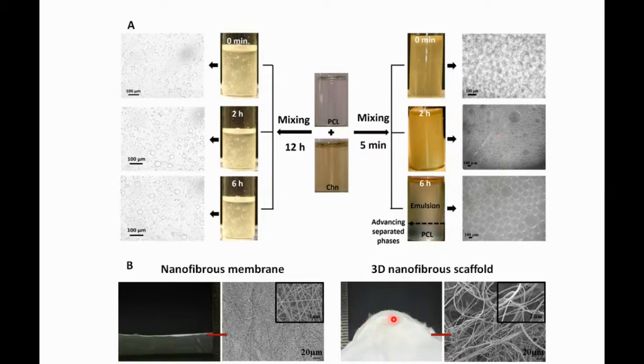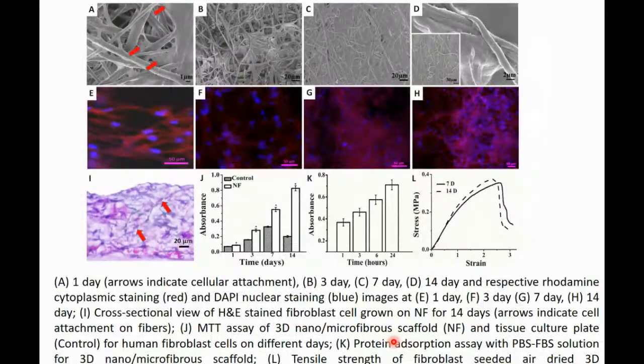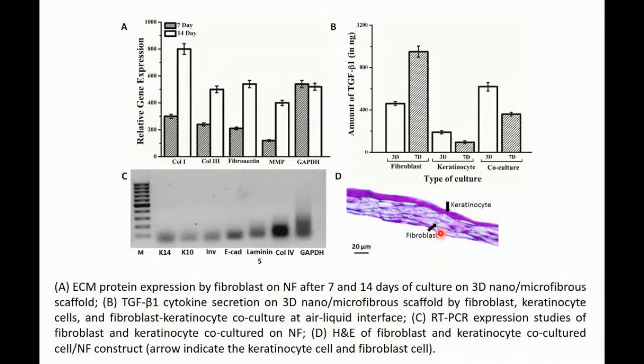Now, on the top of the floppy mass, if you can have a nanofibrous membrane, then you can have controlled porosity. And then if you can infiltrate collagen in the macroporous side, then you can actually have a bilayer structure. And this can be used as a skin graft. As you see here, we have done the study and we have done the co-culture. You can see there is a compartmentalization of keratinocyte and fibroblast, and we have done gene expression and transcriptomic studies, and from there we find the expression of E-cadherin, laminin, collagen 4, involucrin, keratin 14 and keratin 10. It shows that this works wonderfully, and also there is a significant amount of skin maturation.